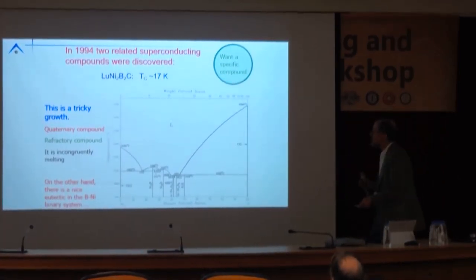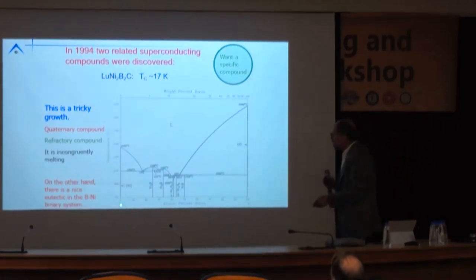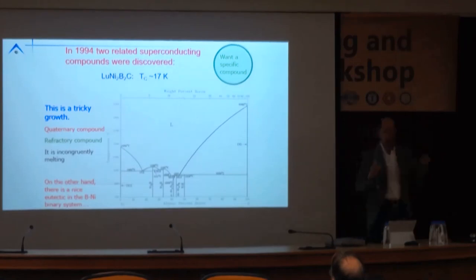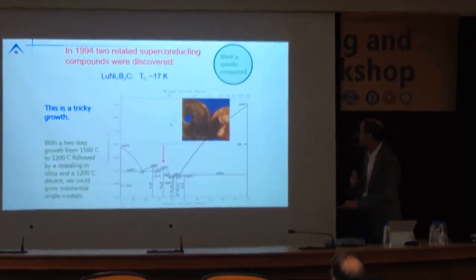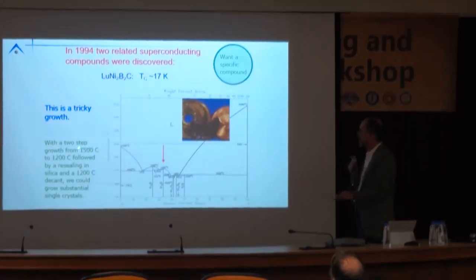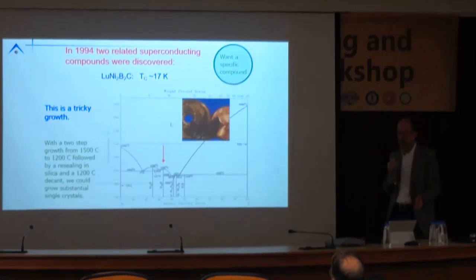But we had a strong drive to try to make it, and after studying the phase diagram and a couple dozen growths that didn't work, I appreciated that if you look at the nickel-boron binary phase diagram, so here's composition, here's temperature, you have this cascade of eutectics below 1,200 that offers you a liquid you want to be able to grow this material out of. So we devised a two-step process, where we would cool from 1,500 to 1,200, we would quench to room temperature, reseal, and then heat to 1,200 and decant, and get large, beautiful single crystals of lutetium nickel borocarbide.